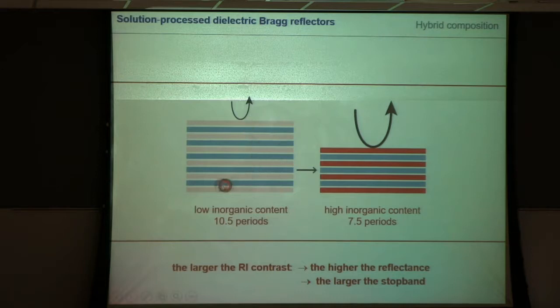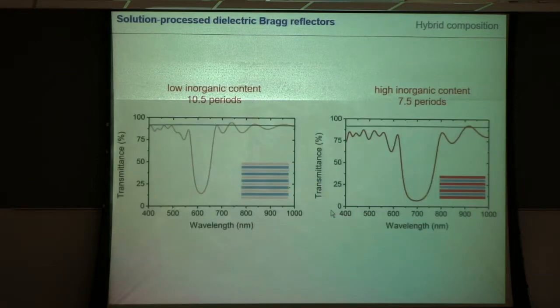And in our case, we can tune this, not only changing from PMMA or polystyrene, but of course, what is nice, without changing really the processing, we just can change the content of the hybrid, and like that, change the refractive index contrast. So here we have a high inorganic content material. We needed 7.5 periods to get to a reflection of like 10, a bit less percent, a relatively broad stop band. Once we use a lower content hybrid, so a lower refractive index contrast with the PMMA, the stop band gets more narrow.